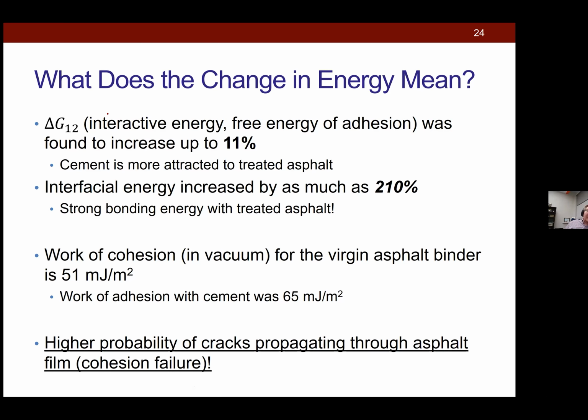So now this is telling us that great, you can do whatever you want to improve the bonding. It's not going to help you because the cracks are still going to propagate through the asphalt, right? And so this is really why we don't see any effect of, for instance, adding silica fume. All right, so even if you're adding silica fume, yeah, great, you're improving the bulk paste strength and durability. Yeah, but your cracks are still propagating through the asphalt. You haven't fixed that problem.